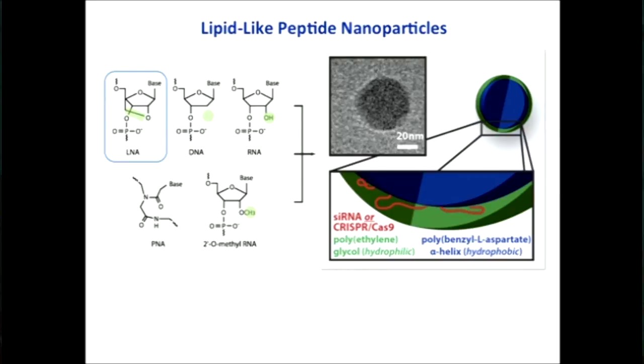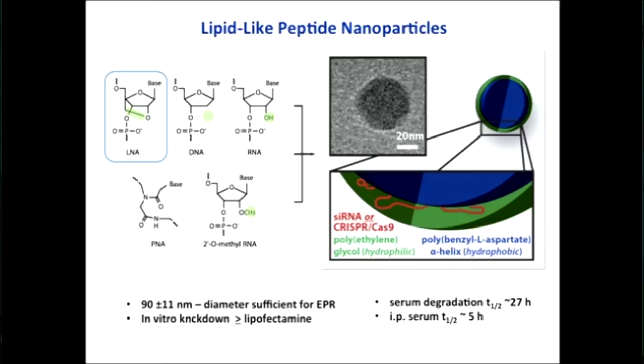we can actually generate a system which forms a micellar particle, and these are actually relatively small. This is a 20 nanometer bar. It's a little harder to see here, but there's a bit of an outer shell around this region, and that is our stealth layer of polyethylene glycol. siRNA is adsorbed within this layer, and we can then use this as a delivery vehicle for siRNA. We refer to these as lipid-like peptide nanoparticles. They're about 90 nanometers in diameter, so they can actually fit in this enhanced permeation and retention. And they have a fairly long blood half-life. They can survive in the bloodstream for a fairly long period of time.